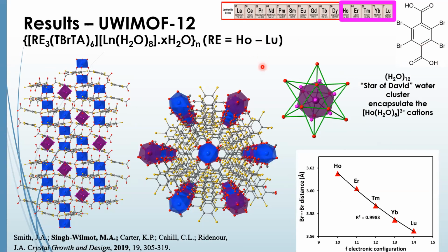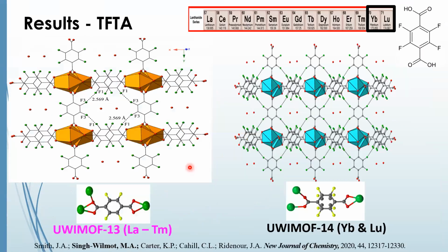The holmium to lutetium featured some very nice, aesthetically pleasing water clusters, which were trapped in the pores of this MOF. We call this the Star of David water cluster, which was encapsulated inside the framework. This was a holmium octa-aqua cation. These were trapped inside the pores of the framework.